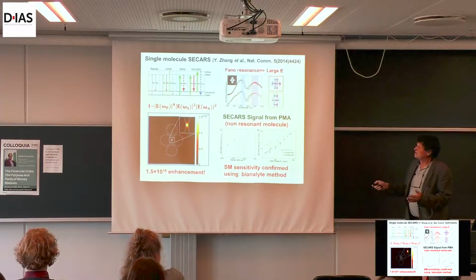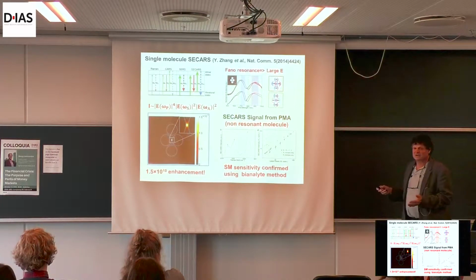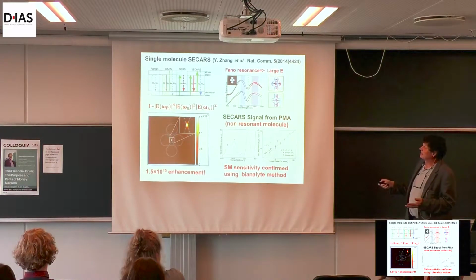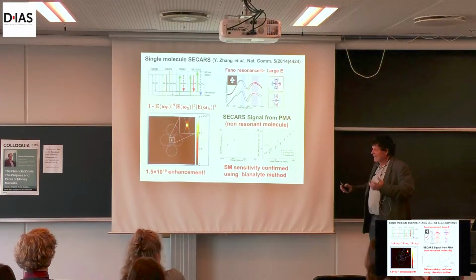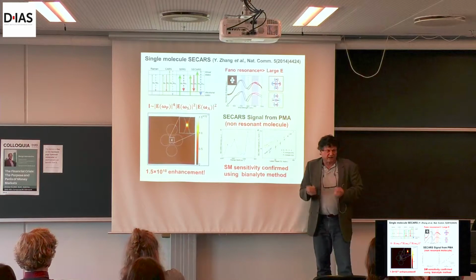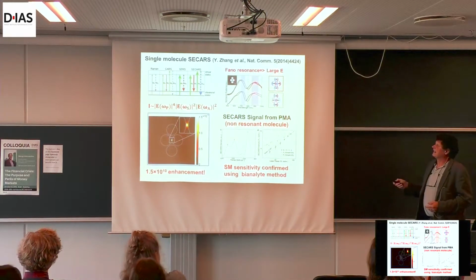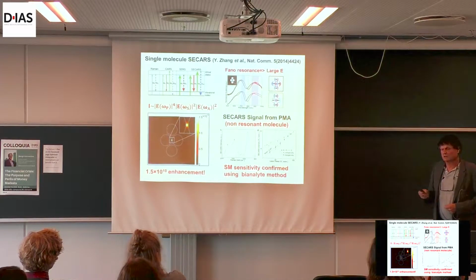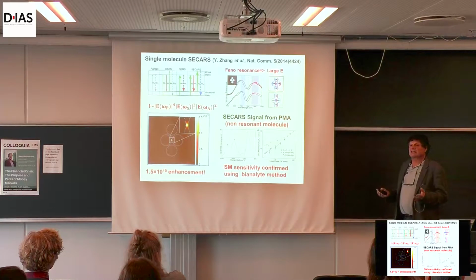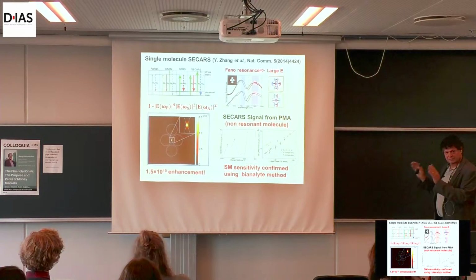So suppose we have a spectroscopy that goes to the 8th power of that amplitude, well, then we have 10 to the 16. So this plasmonic nanostructure, with the ability to provide sub-wavelength focusing and these very large field intensities, can amplify this type of spectroscopy to such an extent that you can distinguish an individual molecule. And this happens from our group.